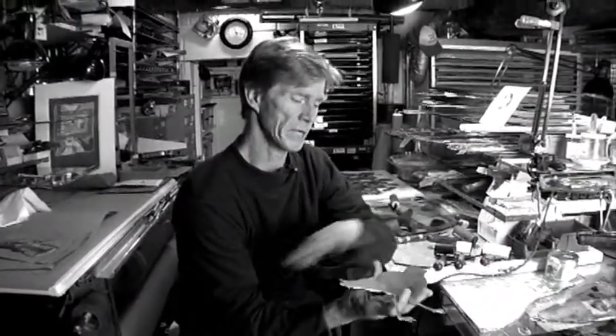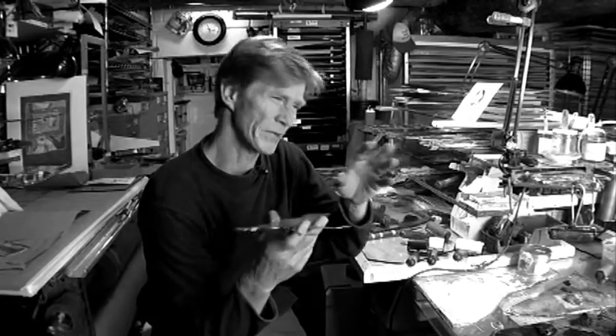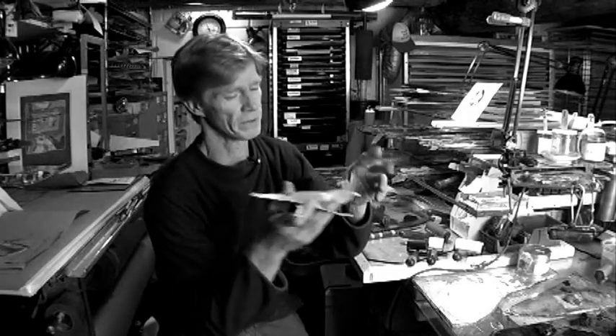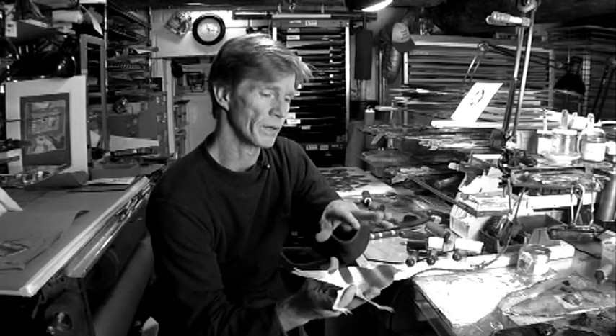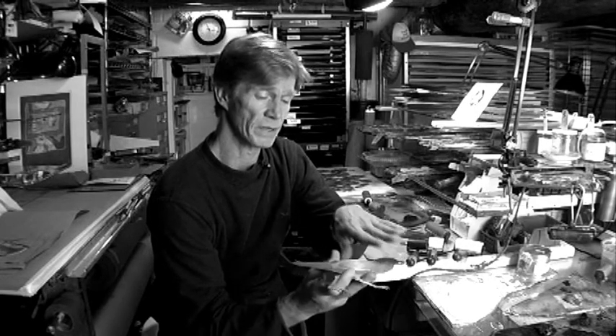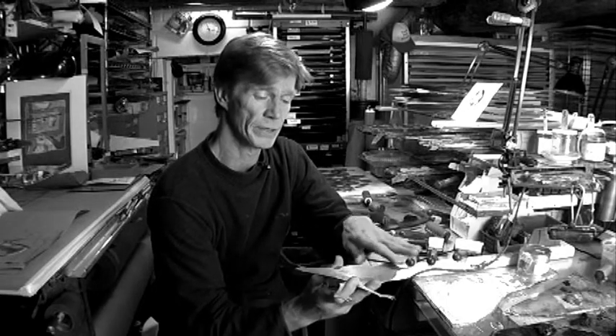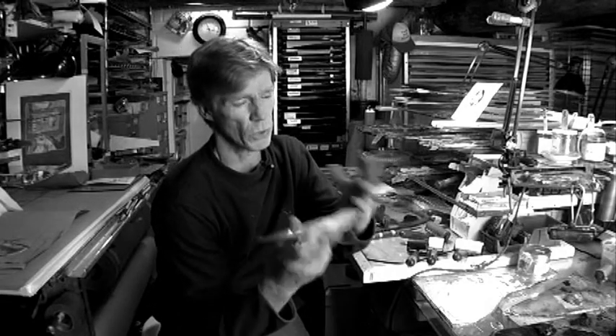I'm treating a copper plate more like a woodblock — first cutting the plate out of ordinary copper, then incising a topography into the plate using acids. It's not really acids, it's ferric chloride — an environmentally safer product to erode copper like an etch. I'm covering parts of the plate with a waxy tar called asphaltum and timing it in this acid bath to give the plate a topographical sense — building different plateaus, hills and valleys into the plate in a three-dimensional sculptural form.